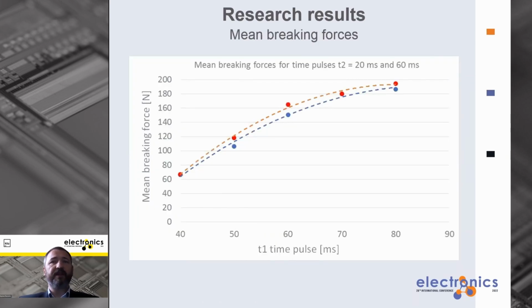After a series of tests, we can notice that the preheat time pulse has a decisive influence on the weld strength. The second pulse does not improve significantly the overall mechanical strength of the welds. Moreover, the increase in the breaking force is stabilizing, as we can see here. The maximum breaking force obtained during the tests without cell damage was equal to 194.5 newtons for the current pulses of T1 80 milliseconds and T2 60 milliseconds on this one. Such a weld has sufficient mechanical strength for the battery pack construction purpose.